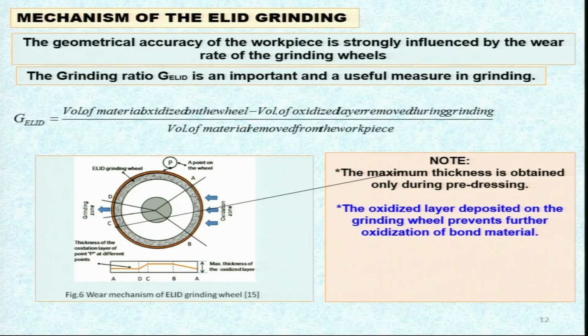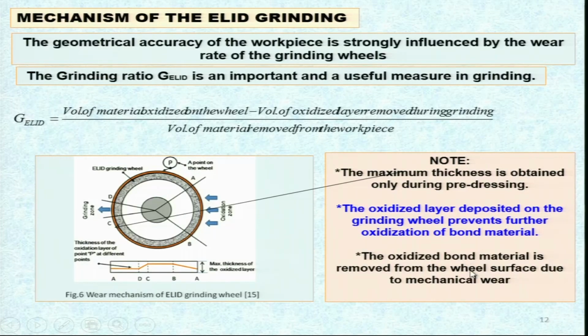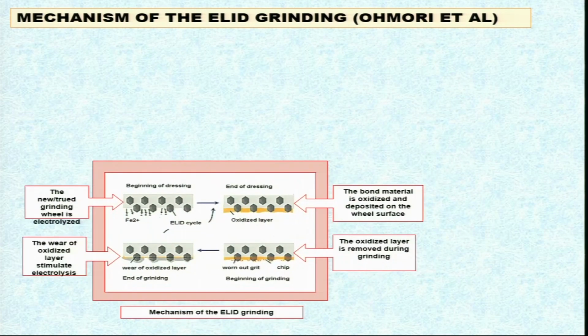The oxidized layer deposited on the grinding wheel prevents further oxidation of bond material, because the oxidized layer is non-conductive. The oxidized bond material is removed from the wheel surface due to mechanical wear, that is, due to the forces being applied by the abrasive particles on the oxidized layer. Mechanism of the ELID grinding, Ohmori et al. They published a paper based on this.